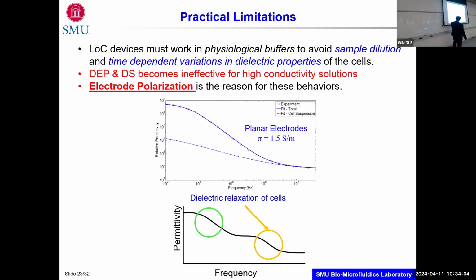Technically, if I'm making an experiment, that's our experimental data, and the fit is the fit of our model, and then we would like to extract what's happening to the cell suspension in these conditions. I forgot to tell you: 1.5 Siemens per meter, high conductivity buffer. This is not what I expect. Theoretically, I would expect polarization of the electrodes and then polarization of the cell membrane, which is what we call beta dispersion. This is what I was trying to measure, which means that the data has to come flat, and then do this, and I cannot see that in my measurements.